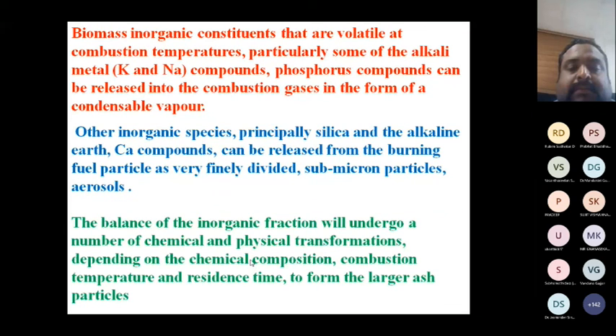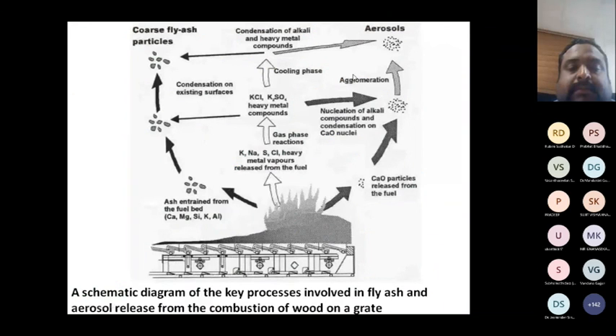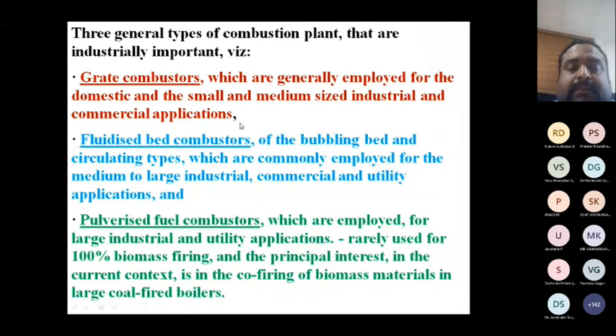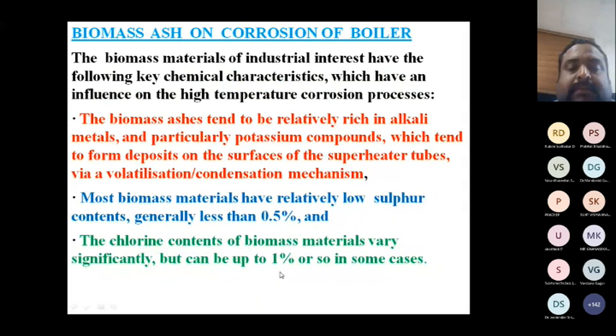Biomass inorganic constituents that are volatile at combustion temperature, mostly alkali metal, sodium and potassium compounds and phosphorus complexes, can be released to the combustion gas in the form of a condensable vapour. It's going as a vapor. Then something also goes as aerosols. For example, calcium compounds go as aerosol. The rest of the things go as large ash particles. These are the three types of combustor: grate boiler, fluidized bed boiler, and pulverized fuel combustion boiler. Now we're looking at the corrosion aspect in boilers.